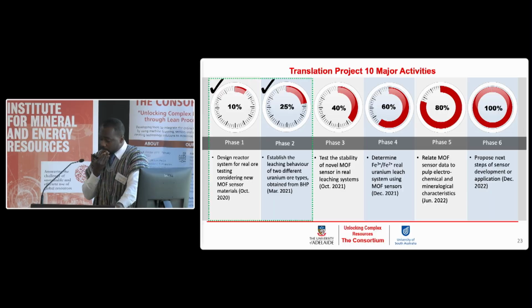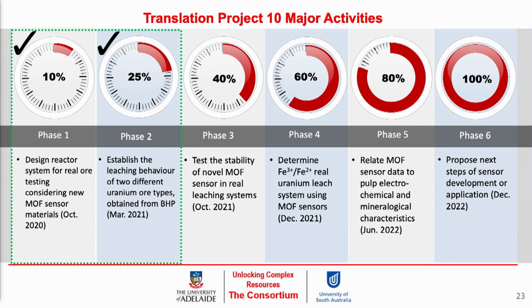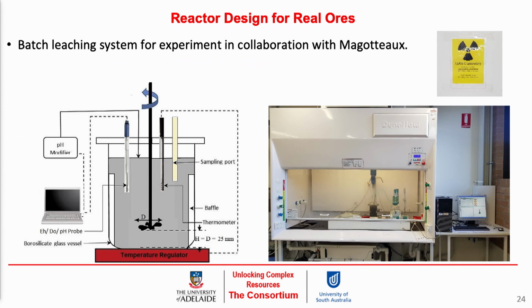For this translation project, we divided it into 6 phases as well. The first one was to get a lab-based leaching rig on site at UniSA, where we can run experiments similar to on-plant and mimic what is done in the industry, and that is done. We also did some preliminary studies on 2 ore types that we received from BHP, which is also done. So we're moving on to testing the MOF sensor once Linda has it ready to be tested in the real ore system, and then propose a next step after that test work and the stability test that can be done on it. So this is how the leaching setup looks.